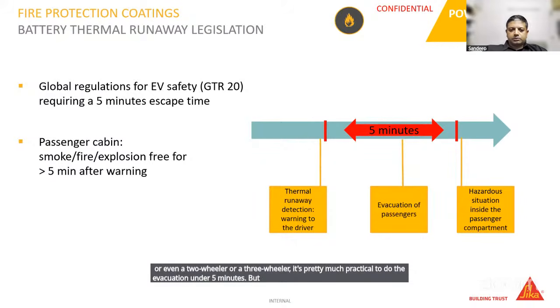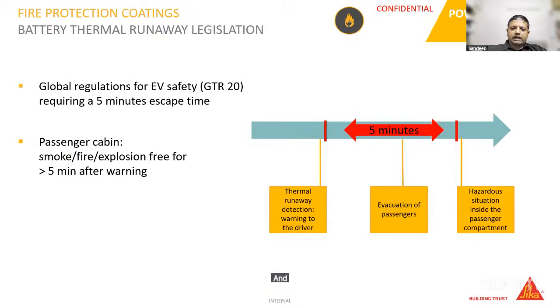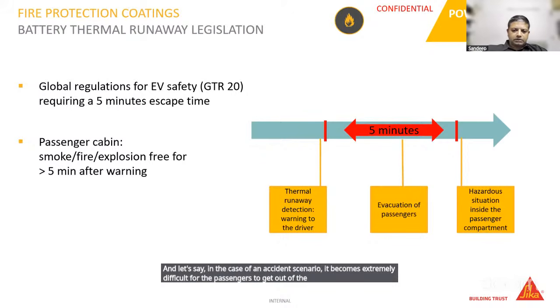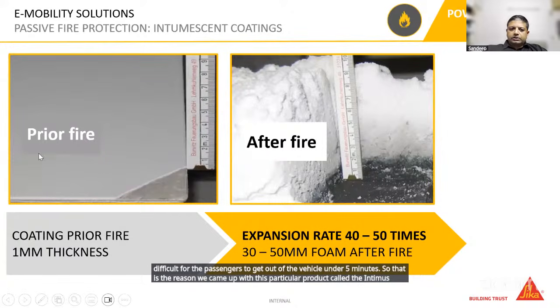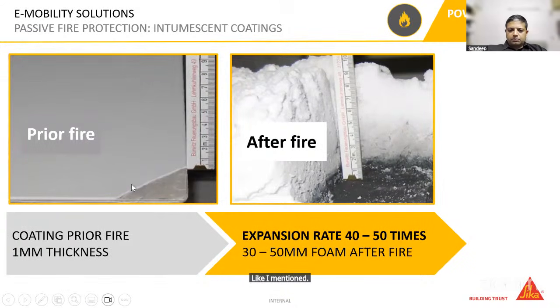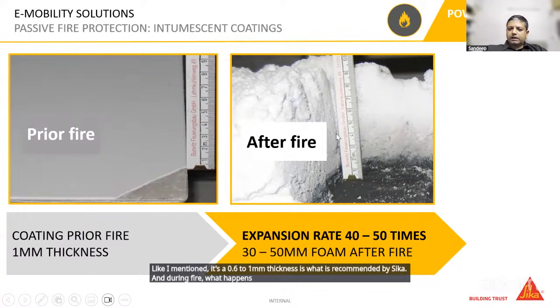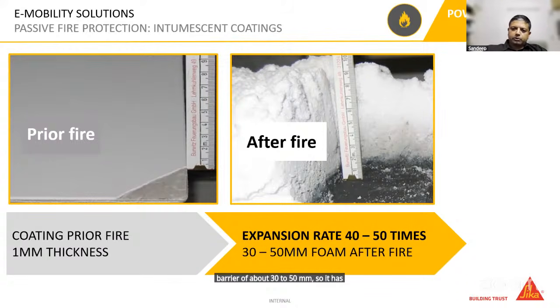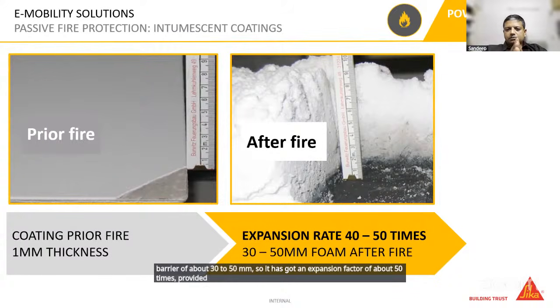But when it comes to public transport like a bus, where typically the pack is at the bottom platform, and let's say in the case of an accident scenario, it becomes extremely difficult for the passengers to get out of the vehicle under 5 minutes. So that is the reason we came up with this particular product called the intumescent coating. Like I mentioned, a 0.6 to 1 mm thickness is what is recommended by Sika. And during fire, what happens? It foams up and creates a barrier of about 30 to 50 mm. It has an expansion factor of about 50 times, provided you have the space for the material to expand. That creates a barrier between the fire side and the non-fire side, which delays the whole process.